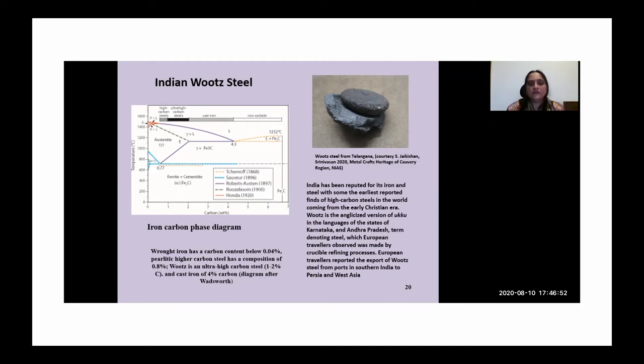And if you look at the iron carbon phase diagram system, now I talked about wrought iron, of course, in the context of the Delhi iron pillar. And wrought iron typically has a carbon content which is below about 0.04% carbon. So we are actually referring to a rather low carbon alloy when we talk about wrought iron. But as we keep adding more and more carbon to the iron, the properties change. And perlitic high carbon steel, for instance, has a composition of about 0.8% carbon. In today's terms, that is seen as a medium carbon or high carbon steel, actually, because as you keep adding carbon, of course, iron gets harder and improves the properties of ductility and so on.